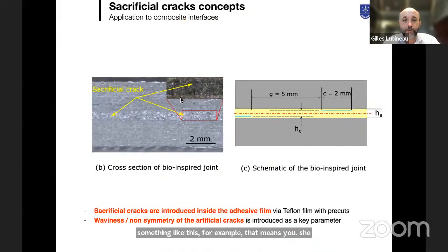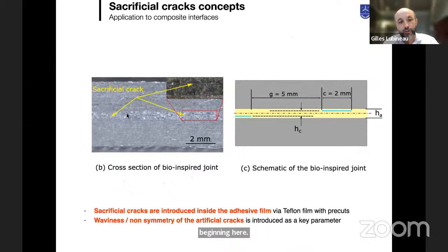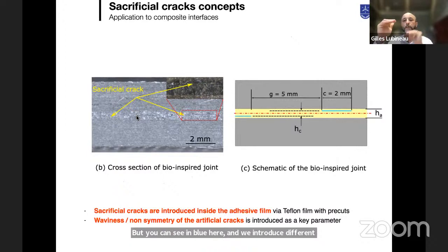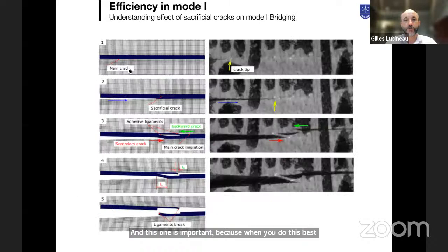It's when you do something like this, for example. Here what we do is not very clear on the picture, but here you have two substrates, and in the middle there is an adhesive layer, and here you introduce a sacrificial crack. That means that there is a Teflon film from the beginning that you can see in blue here. We introduce Teflon films that are going to be cracks from the beginning. This is important because the role of these sacrificial cracks is to make sure that we introduce crack bifurcations and we modify the failure mechanism.